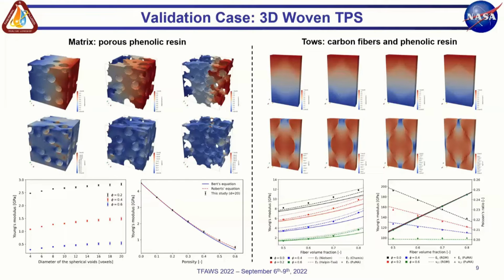The plots on the right represent the Young's moduli and the Poisson ratios in the longitudinal and transverse directions for the different fiber volume fractions and matrix porosities. And we can observe also how they compare against the validation expressions. I don't want to spend too much time here, but we can observe how, for example, for the transverse direction, higher volume fraction and lower matrix porosities lead to higher Young's modulus. And how the PUMA results, which are the dots in this plot, fall in between the approximations from Halpin-Tsai, Nielsen, and Chamis.